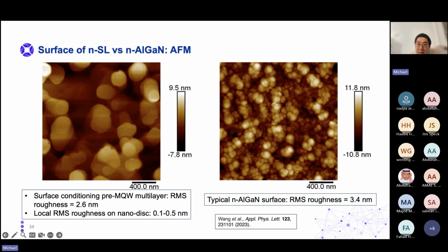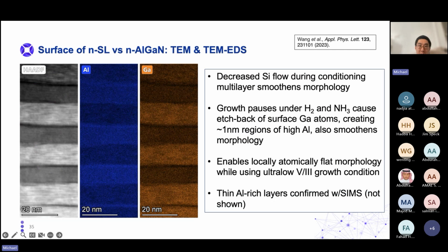So this is our typical n-type aluminum gallium nitride surface, which has an RMS roughness of around 3 to 4 nanometers. And with this n-type smoothing layer, what we got was a little bit less overall surface roughness, but a lot less roughness on top of these nanodisk formations. So here's a cross-sectional transmission electron microscope image of our n-type smoothing layer, and you can see that with these pauses, we form these regions that have more aluminum and less gallium, and this definitely helps the morphology to locally smooth out. And that helps the interfaces between the quantum wells and quantum barriers on top.